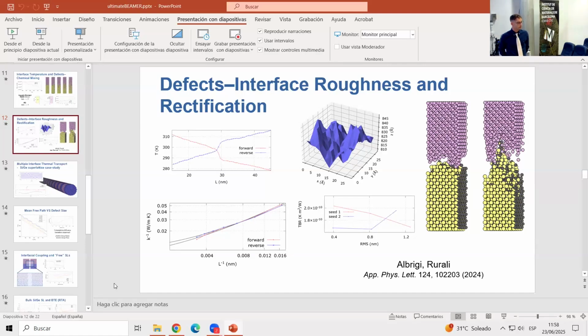And if I understand this correctly, there are two effects that might play a role in explaining this rectification. One is the fact that the thermal conductivities of the two materials display a different temperature dependence, meaning that the conductivity when one side is hot might change differently than when you swap the temperature profile. And then there is the fact that the available vibrational states are different at different temperatures, so the acoustic mismatch might be different when the temperature profile is reversed. So which of these two effects do you think explains your rectification? The first one, definitely the first one.